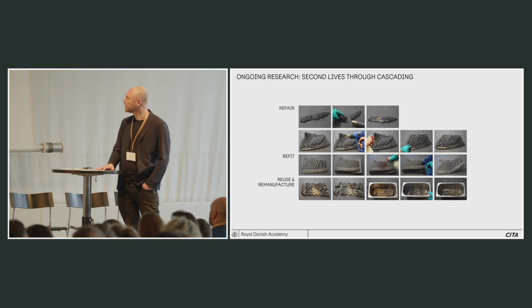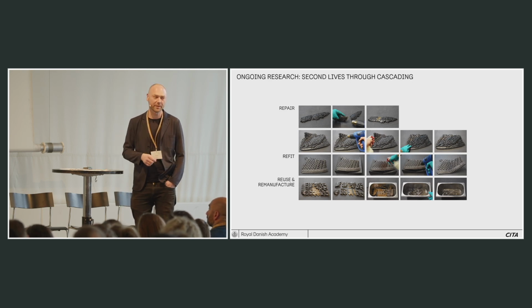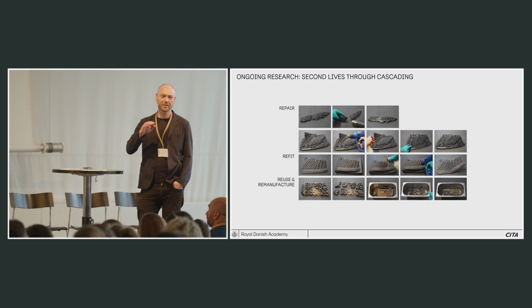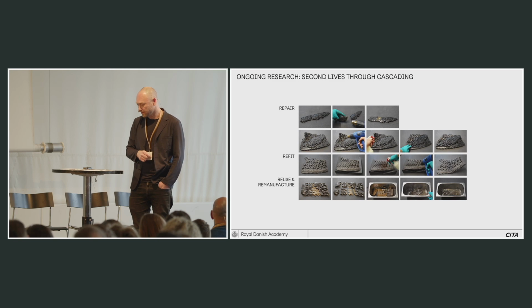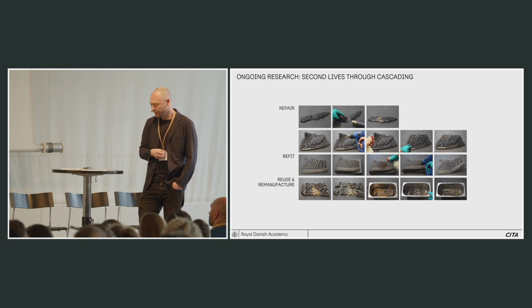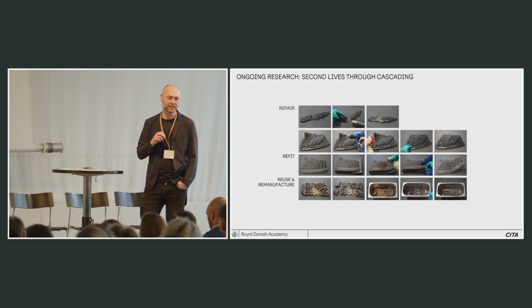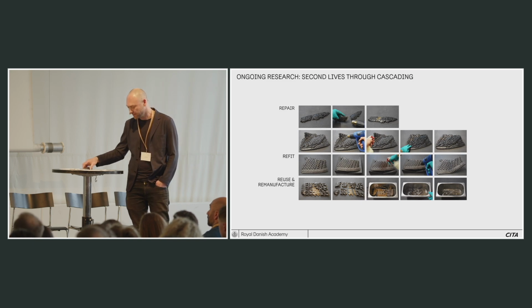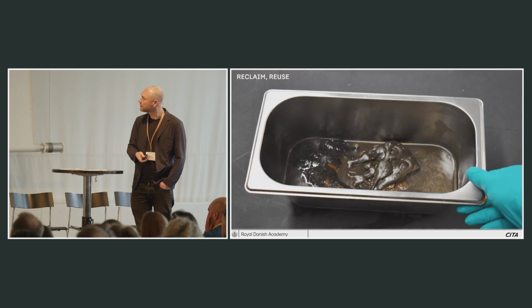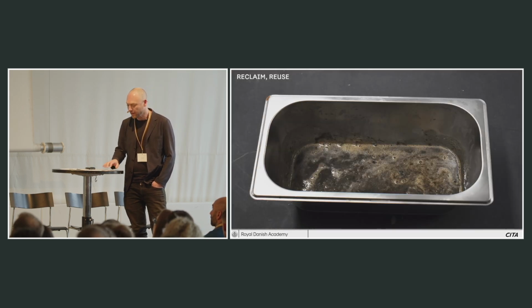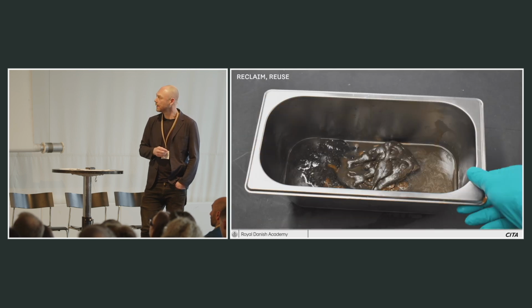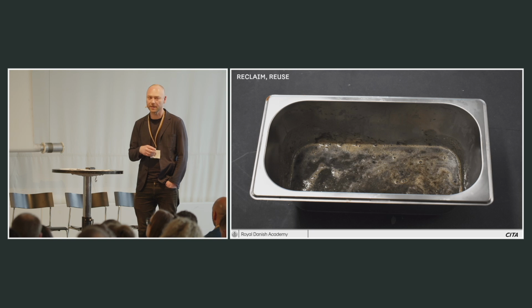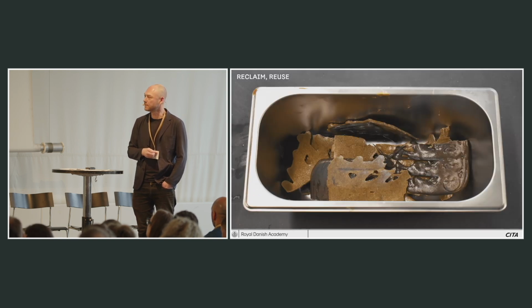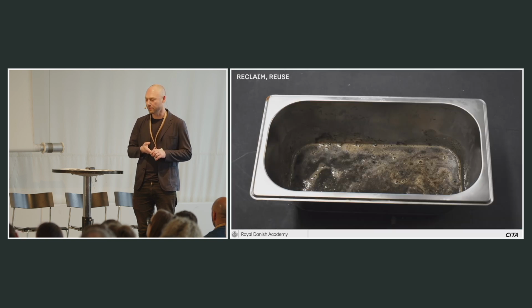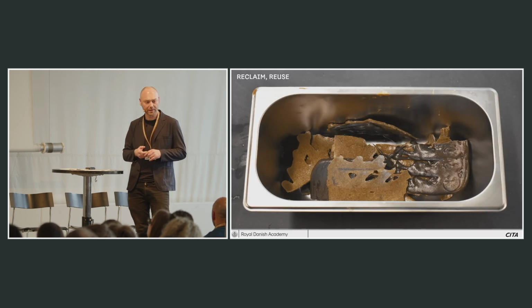So beyond the initial making of the objects, and slightly beyond what's described in the article, it's also important to say that there's another wrapper around the research that focuses on how we can cascade and reuse this material. So how we can give it a long life by strategically activating the same thermoplastic-like behaviors as we use when we initially print the material. At a lower level of that cascade, we're able to reapply heat and water and perhaps top up with some glycerol to melt down and reuse exactly the same material ingredients, whether it's a print mistake or a panel that can become another object.